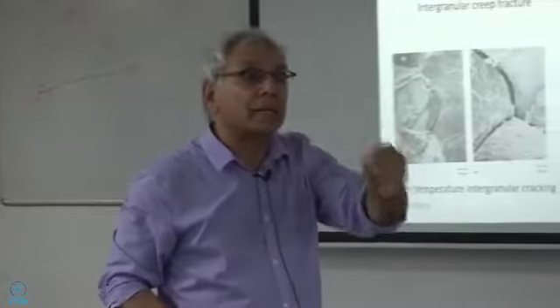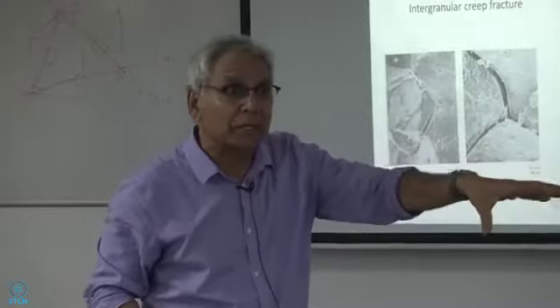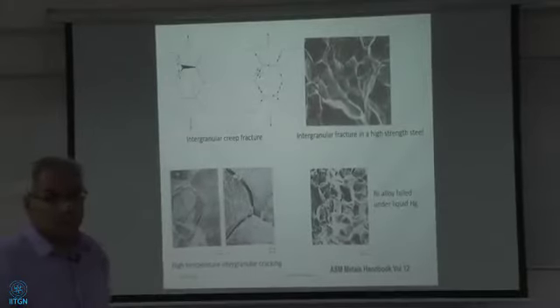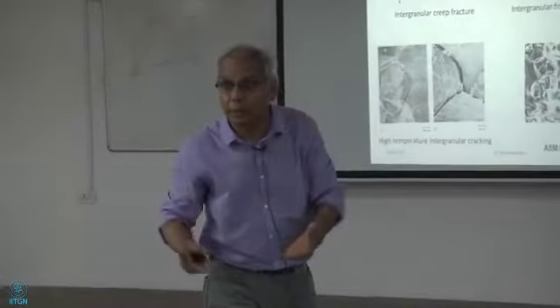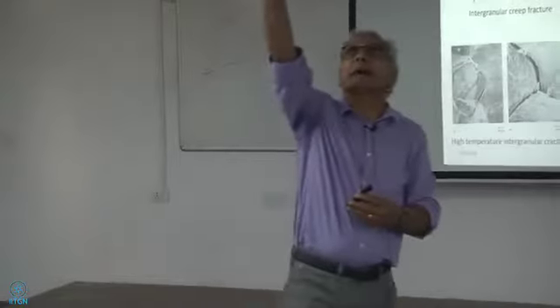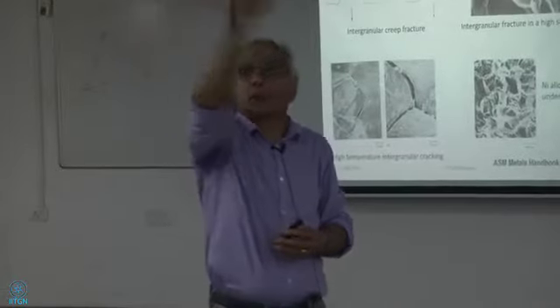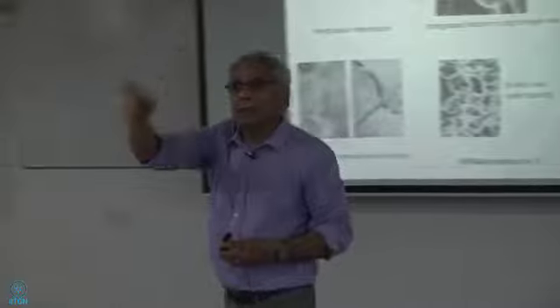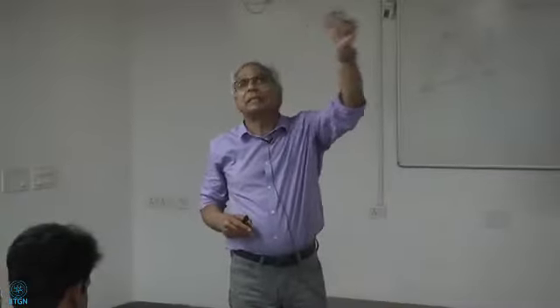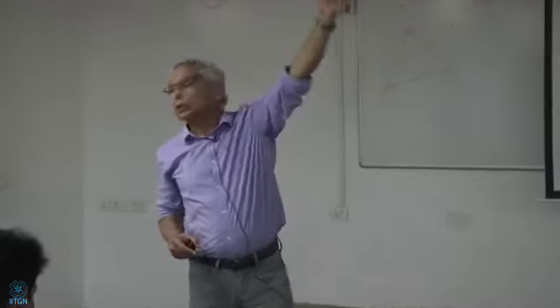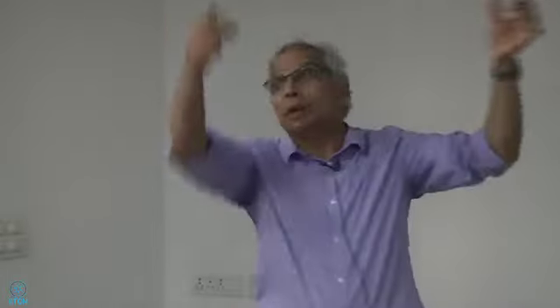So you come across the intergranular fracture in the one situation that I just mentioned. The other situation that you come across is in creep, high temperature creep. At very high temperatures, when a structure is undergoing creep loading, like if you take pipelines, for instance, right behind this wall, I'm sure there are pipelines that are carrying hot water to the bathrooms and all that, right? So if you can imagine for a second, instead of the hot water, you have superheated steam going through those pipes, you can have creep because the superheated steam will have a very high temperature. Then you've got loads because there are hangers. The pipes are hung, there are hangers between every so much distance, right?